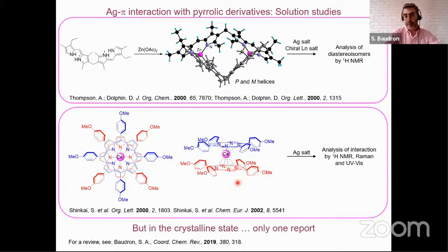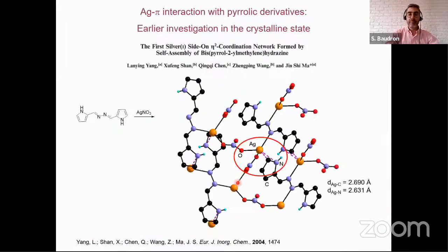As a matter of fact, to the best of our knowledge, there was only one example that had been reported by the group of Ma, where they investigated this type of ligand and its assembly with silver nitrate. They obtained a crystal structure of a resulting network, and they showed that in this case, the silver sits not on top of a carbon-carbon double bond, but on top of a carbon-nitrogen bond with a distance of about 2.6 to 2.7 angstroms. And this is worth remembering because I will come back to that. So it seemed to us that while this had been heavily investigated with aromatic and polyaromatic systems, there were way fewer reports with pyrrolic systems.